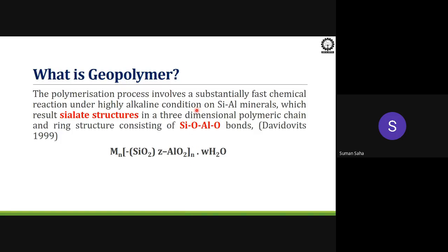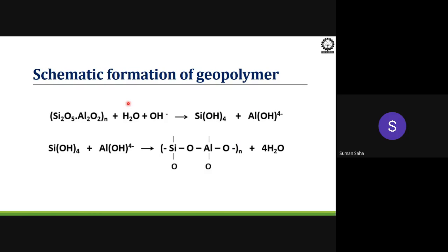I will show you the schematic reaction. This is the fly ash or GGBS, a silica-alumina rich material. And this hydroxyl ion and H2O we get from the alkaline solution, and it will first form silicate and aluminate, and this silicate and aluminate react together to generate this bond and provide strength like cement.